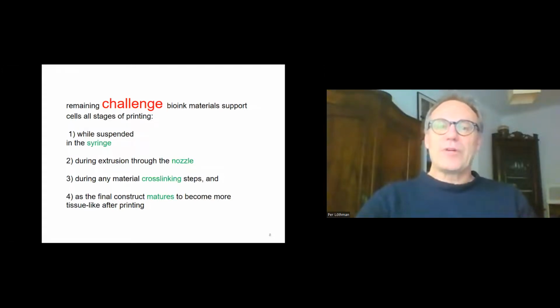It can also be, for example, that we need a certain property of the bioink in order to prevent sedimentation. And during extrusion through the nozzle, that's what I just mentioned, right? The shear forces and the flow profile may rupture cell membranes during any material cross-linking step. Cross-linking is something we sometimes need post-printing in order to make the printed construct stable. We might want to cross-link the polymers that are contained in the heart or liver, right? As the final construct matures to become more tissue-like after printing. Those are challenges that we all face in general.